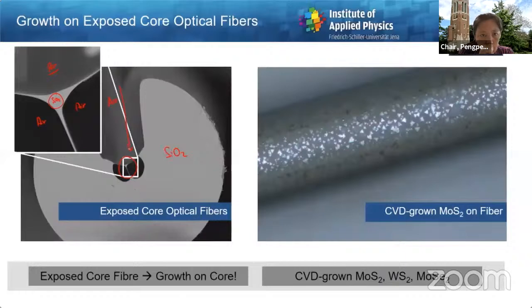The important part here is that the top surface is exposed to the outside world. And if you place it in your CVD reactor, you will observe growth of transition metal dichalcogenide crystals on the surface. And this can interact with your guided mode by means of the evanescent field of this guided mode, which sticks out into the air region and therefore interacts with your transition metal dichalcogenide. We have tested this approach, and it works for quite a lot of transition metal dichalcogenides. In one image on the right-hand side, you have the optical fiber, so an experiment light propagates this way.